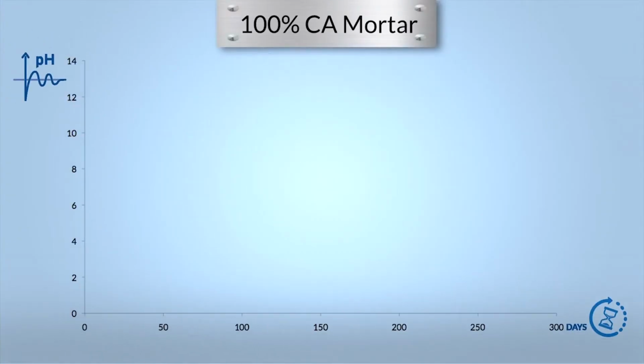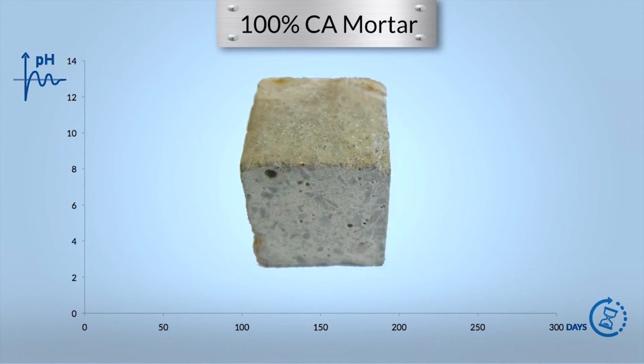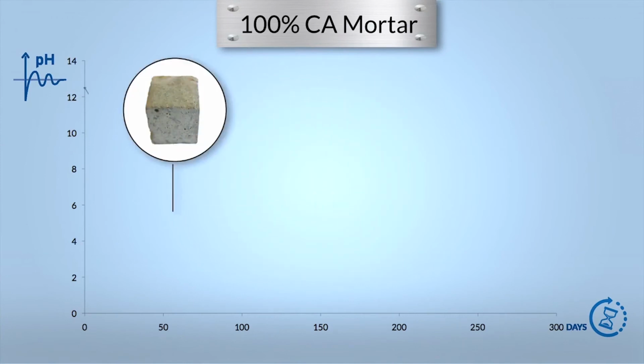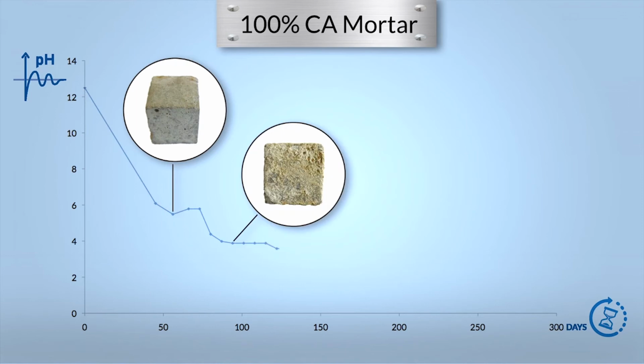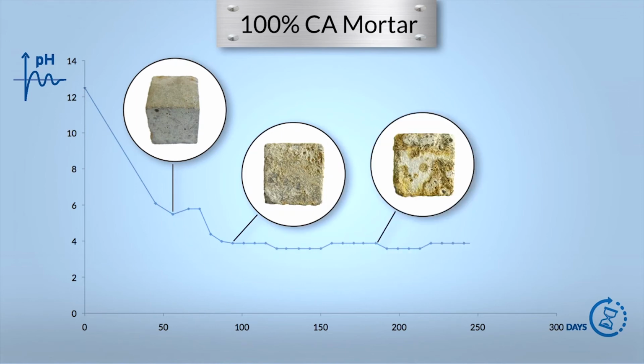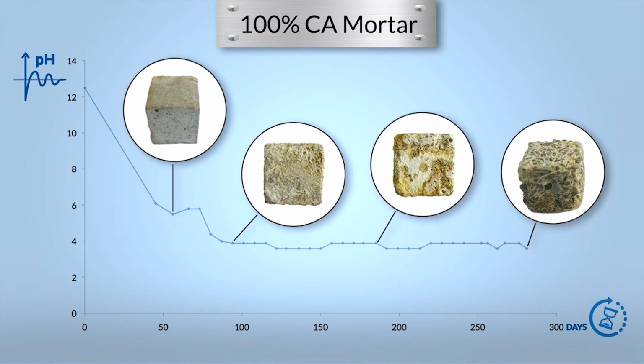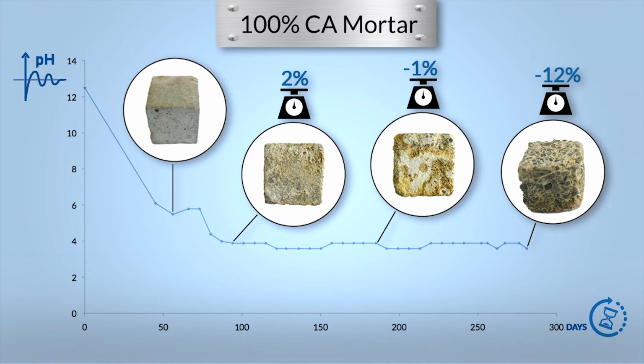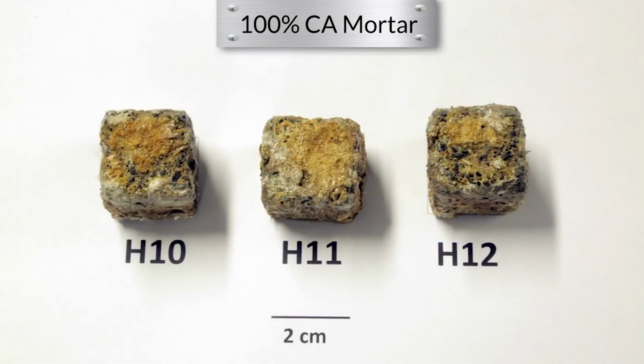This last series is made with 100% calcium aluminate mortar, made not only with calcium aluminate cement, but also with calcium aluminate aggregates. This unique chemistry provides the best resistance possible to H2S biogenic corrosion. The surface pH is also stabilized around 3.8, and the weight loss after 9 months is 12%, the lowest weight loss of all series put at test.